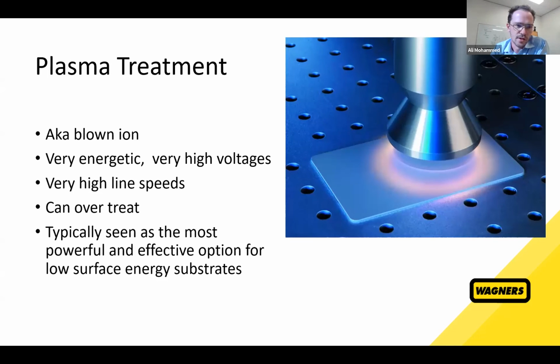And then the third one, and probably the one that's considered the best, so to speak, is plasma, or blown ion, it's called. It's a very energetic, very high voltage type of surface treatment. It can achieve very, very high line speeds because it is so energetic. It doesn't need much time to increase the surface energy of a substrate. However, it can overtreat if you're not careful and you haven't calibrated your line properly. You can see detrimental adhesion from overtreating with plasma. And as I said, it's typically seen as the most powerful or effective option for low surface energy substrates.